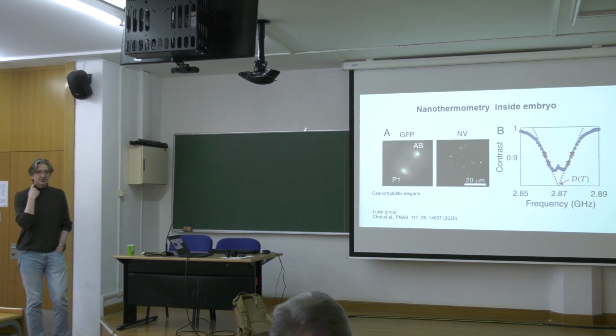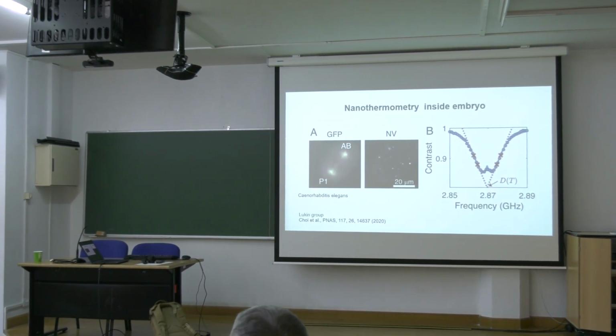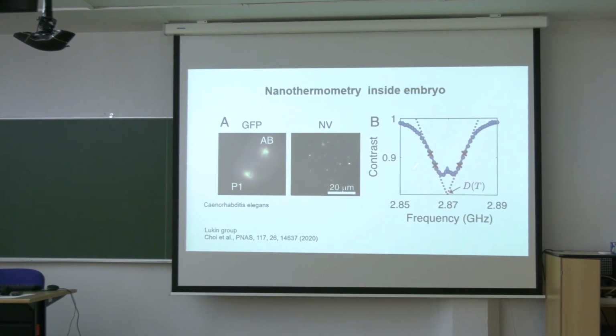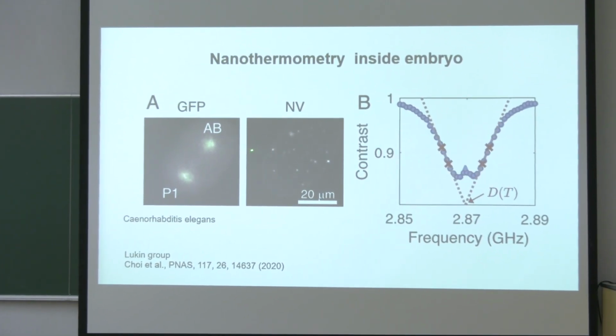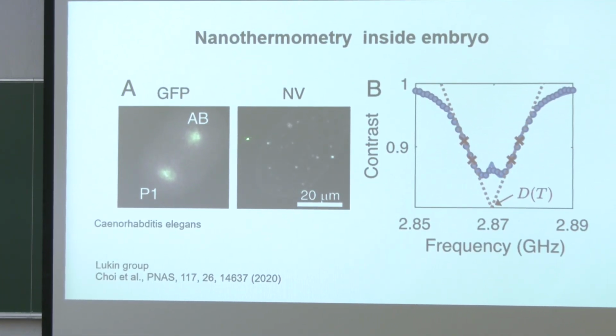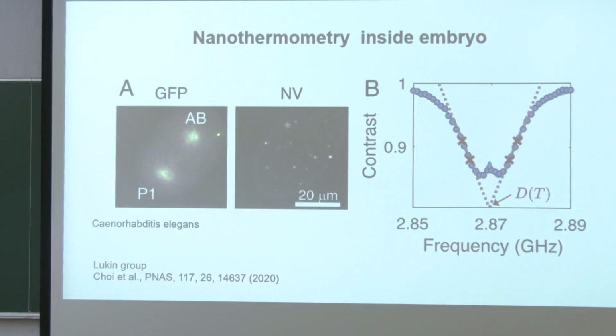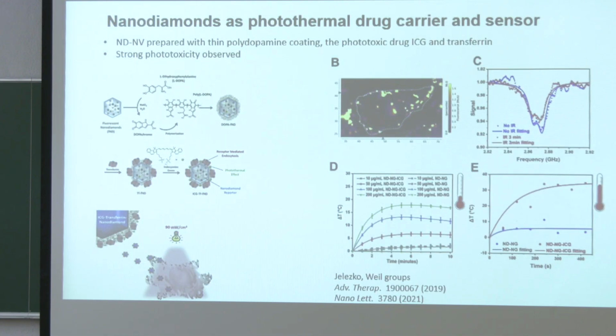For experiments in cells, there was a transfer of this technology inside of living cells. Here I show you the result of the Lukin group, where an embryo was doped with nanodiamonds, and what you see is a division event of a cell in the embryo, where you have these nanodiamonds which were introduced inside of cells on the right side, and they were used to track the temperature with a precision of about 1 degree. So these experiments really can be transferred inside of cells. They can also be applied not only to measuring temperature, but to measuring some functional change of temperature.